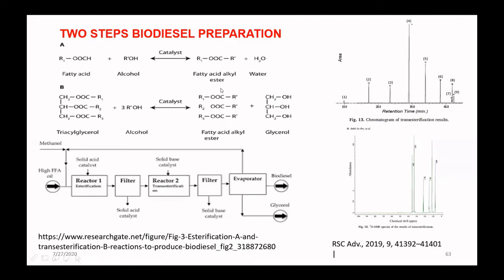We can determine the concentration of the fatty acid ester using GC and also NMR. We have experience using both heterogeneous and homogeneous catalysis in this process. This is the step of biodiesel preparation using two steps. In reactor 1, a solid acid catalyst, then a filter to separate the solid acid catalyst from the system. Then the triglyceride or vegetable oil is treated in the second reactor by a solid base catalyst, then filtered and evaporated. Then we obtain biodiesel and glycerol.